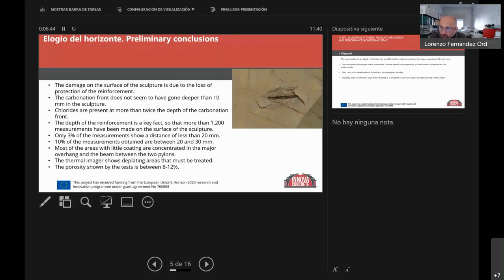So the sculpture had this kind of problem, detachments from the corrosion of the rebars. We didn't know if the problem was carbonation, which is normal in concrete, but we found that the carbonation was only about 10 millimeters deep in the sculpture. So we found finally that the chlorides go a lot deeper into the surface of the sculpture than the carbonation, and that the main problem was the chloride.